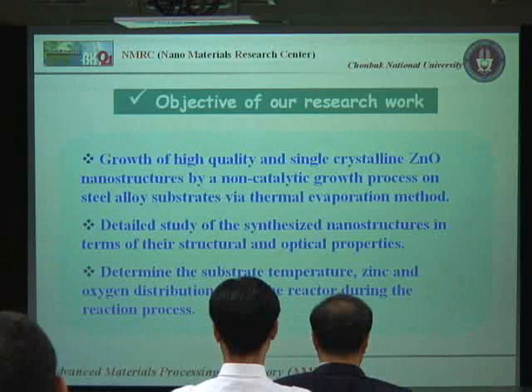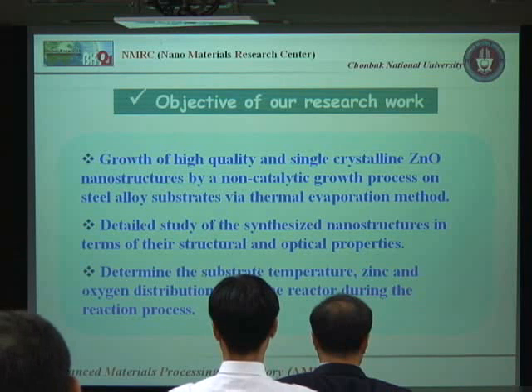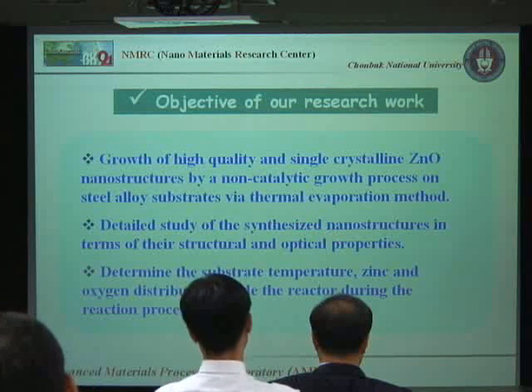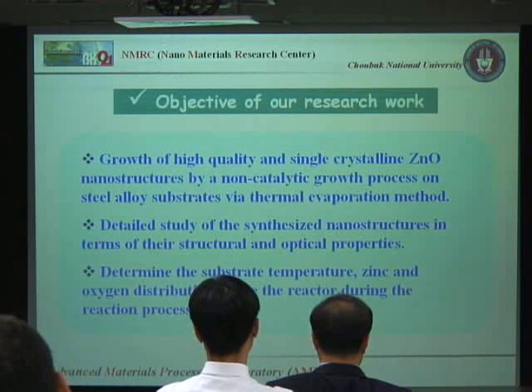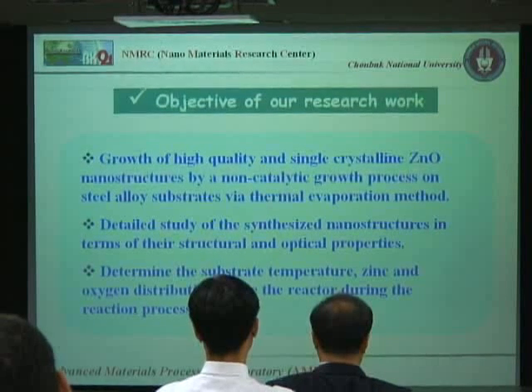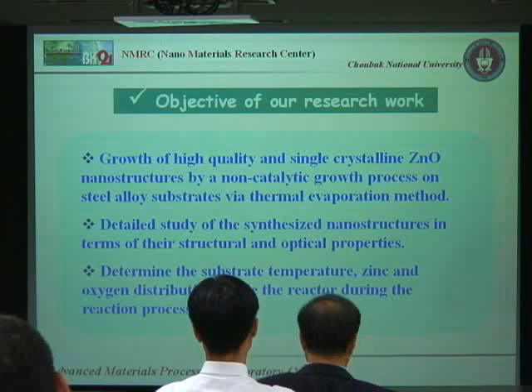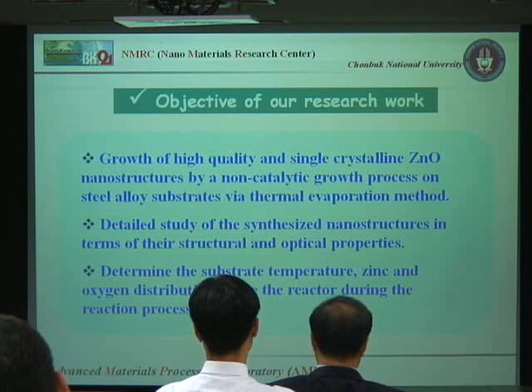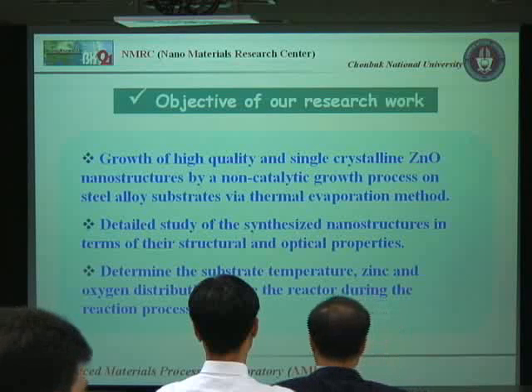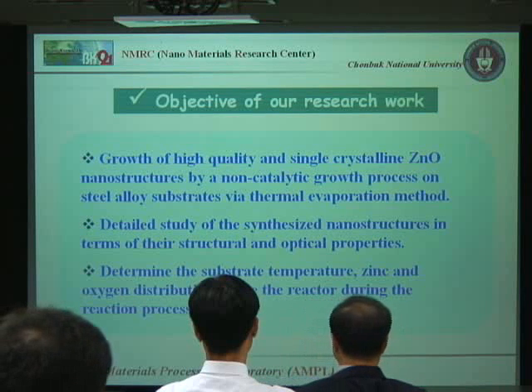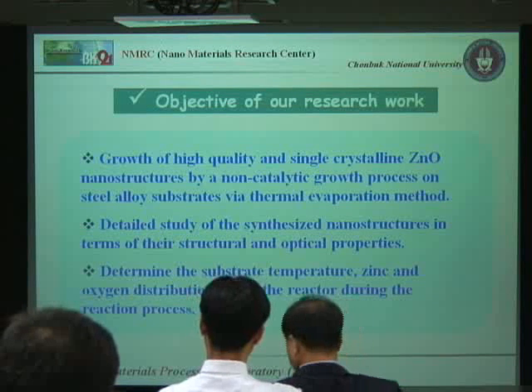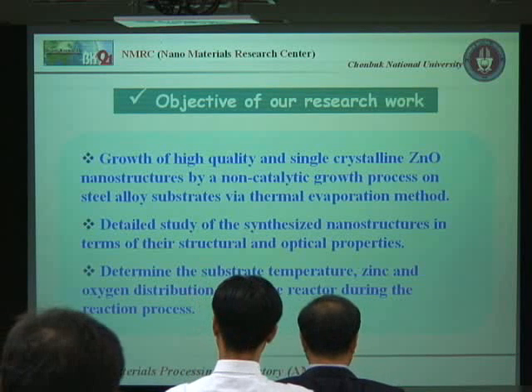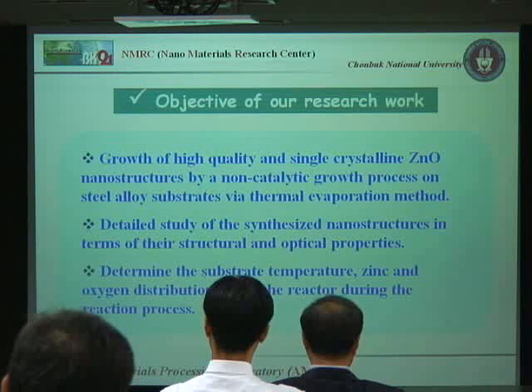The objective of our research work is to grow highly crystalline zinc oxide nanostructures by the non-catalytic growth process on a special substrate like steel alloy substrate via the thermal evaporation process, and to determine its growth mechanism and also the structural and optical properties of these structures, and to determine the substrate temperature, zinc and oxygen concentration during the reaction process inside the reactor. What is the impact of these reaction parameters on the morphology and structure of these nanostructures? We also determine this in this presentation.